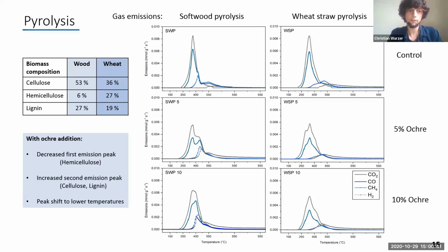What is interesting here is to look at the first peak of CO2 and CO, which is significantly decreasing if you go from the top to the middle to the bottom. This first emission peak is usually typical for hemicellulose decomposition, which you can see is decreasing quite a lot, while at higher temperature, the x-axis representing the pyrolysis temperature from 100 to 550 degrees, the second peak is increasing with ochre addition, which refers to cellulose and lignin decomposition. And that's something iron is known for, increasing the cellulose and lignin decomposition.